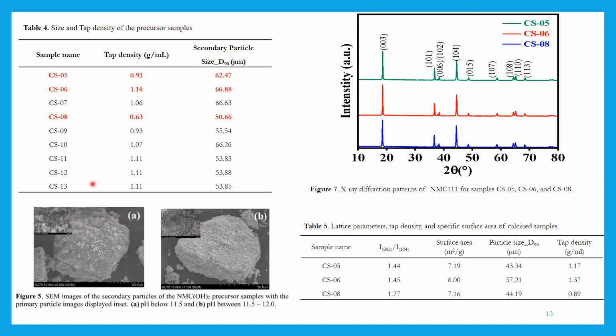And then from these samples, we selected 3 with 3 different tap densities. We lithiated the samples using this process I described earlier. And so before we did battery testing, we looked at the crystallinity of the material. And so we found that there were no impurities. So normally if the manganese hydroxide impurity was still there, it would still be between this range, but we found no impurity.